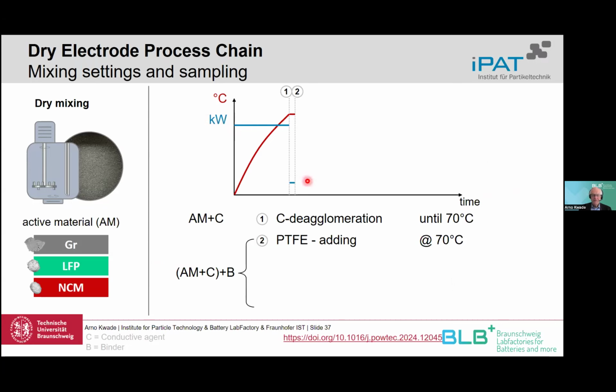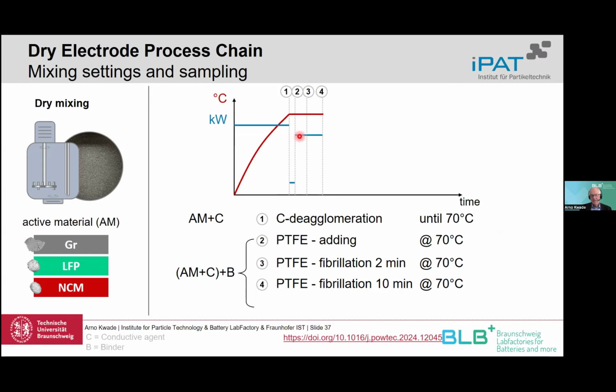Then there's a, let's say, softening phase, and then we come to the fibrillation. So here we add the PTFE, and then we have the first fibrillation of the PTFE, and we take a sample. We have another 10 minutes fibrillation, and afterwards we take sample 4. And then we have a cooling down period without mixing.